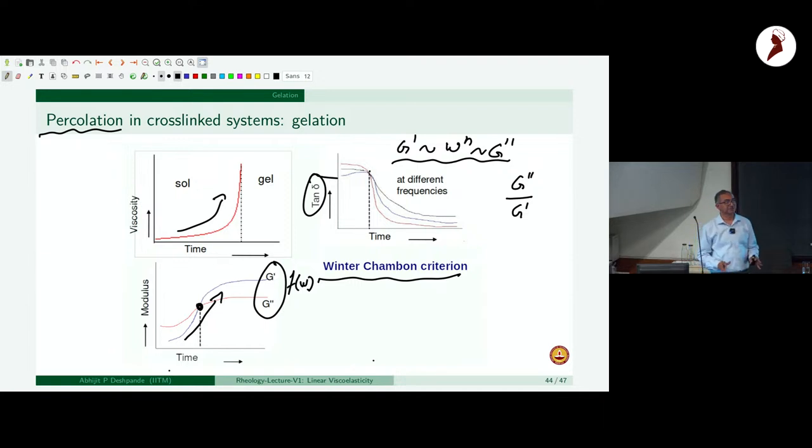And so that can be determined rheologically using what's called the Winter-Chambon criteria, where you would plot tan delta as a function of time. And the time at which the tan delta is basically independent of frequency, where all these runs are at different frequencies. And so this is used many times to try to measure the gel points and looking at what is the power, given that when you form the self-similar gel,